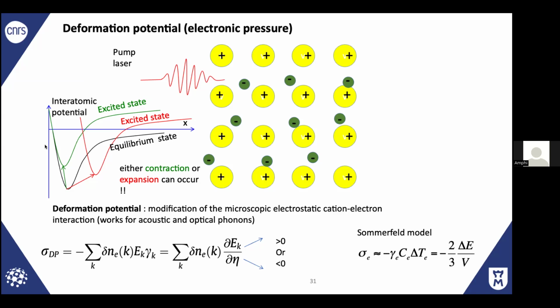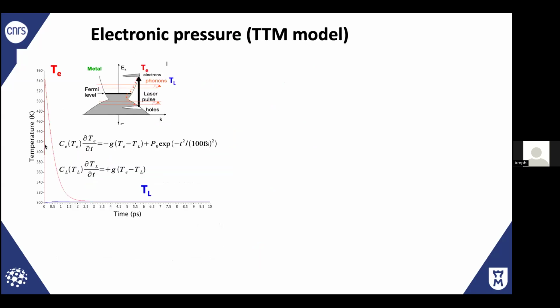And for metals, you can also show that if you modify the electron energy of, let's say, the Sommerfeld Fermi sphere, you immediately induce a pressure, which is electronic pressure. Just a few words about that. This is a two-temperature model. I don't know if people are familiar with that. When you shine light on such metals, you put electrons in high energy levels, and so the electronic temperature is very different. People use the two-temperature model, with a huge change of the electronic temperature. By electron-phonon collisions, electrons relax, and then the energy is converted to the lattice subsystem.